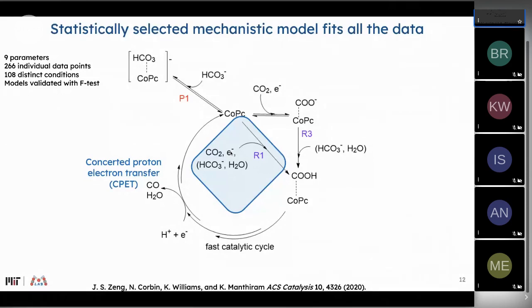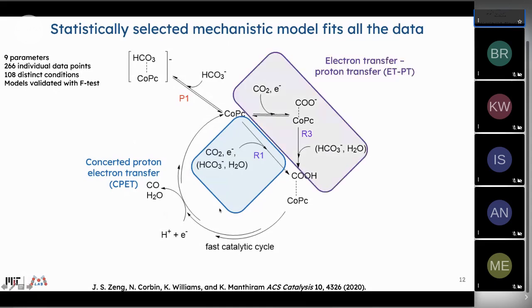In doing this, we find that there are, in fact, 2 pathways through which this system is proceeding: there is a certain regime in which a concerted proton-electron transfer occurs, and there is another regime in which an ET is followed by a PT. So there are 2 different mechanisms at play depending on the conditions at which the system operates. We'll sketch out in more detail in just a moment the 2 regimes in which that occurs.